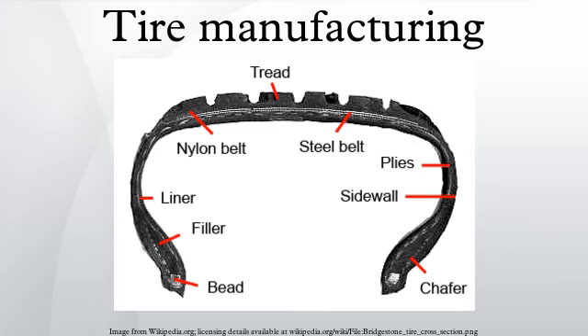The compound is pushed through a die, after which the extruded profile is vulcanized in a continuous oven, cooled to terminate the vulcanization process, and either rolled up on a spool or cut to length. Tire treads are often extruded with four components in a quadruplex extruder — one with four screws processing four different compounds, usually a base compound, core compound, tread compound, and wing compound. Extrusion is also used for sidewall profiles and inner liners.